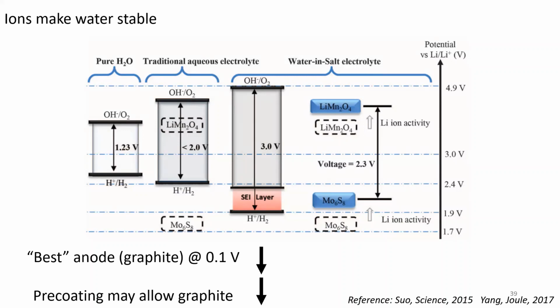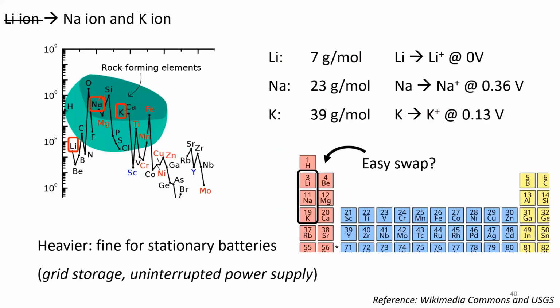Eventually, this group, a couple years later, found that they could put an SEI on the anode ahead of time and then assemble the battery, and they were able to make a prototype that ran at 4 volts. It wasn't durable though. After about 50 or 60 cycles, it started degrading. So we've got water, it's an option.